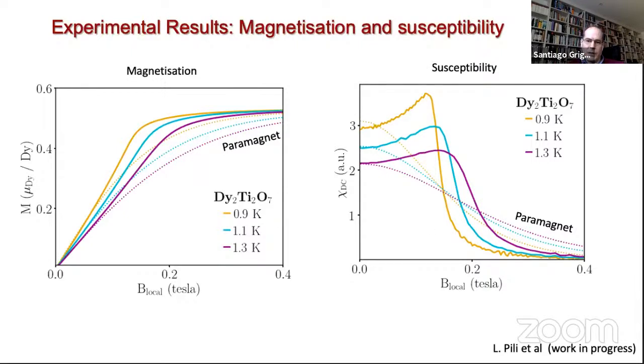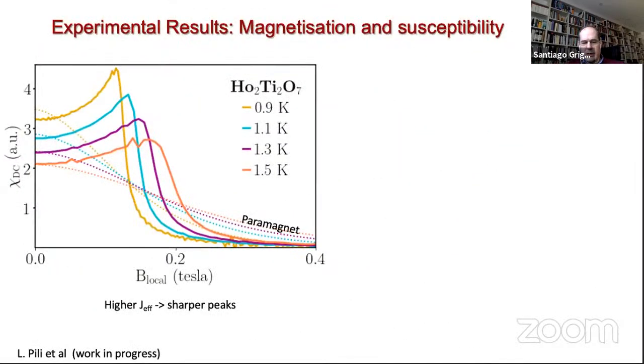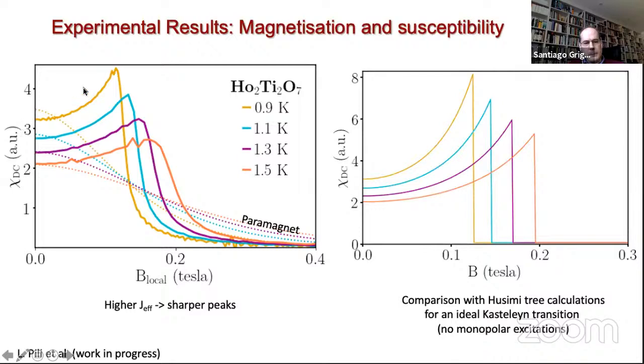asymmetric type of peak. So if you now look at holmium titanate, the exchange constant is higher. So that means that for the same temperatures, you're closer to the ideal limit. And you see that this susceptibility is becoming sharper. So you get better defined, more asymmetric peaks. So now when you compare this susceptibility with the ideal susceptibility that you can calculate in the absence of any type of excitations, you see that they indeed resemble a sort of rounded off version of the ideal Kasteleyn transition.